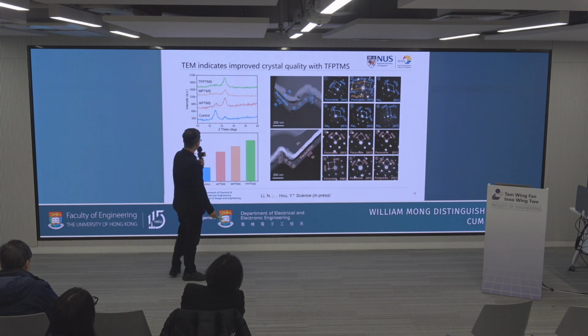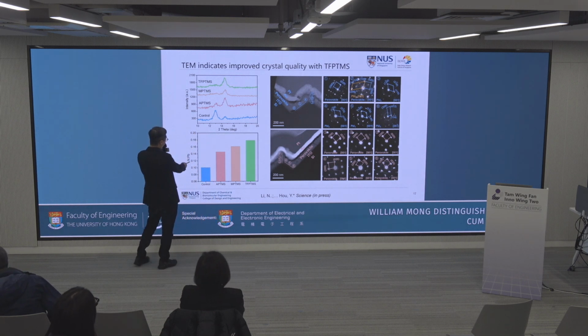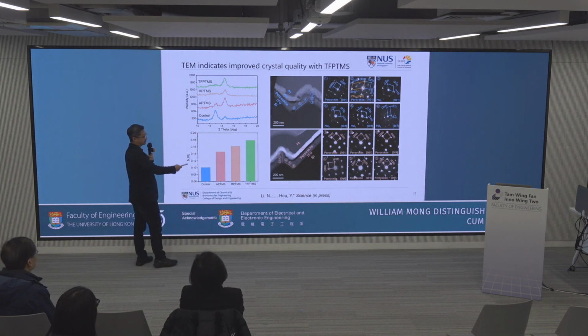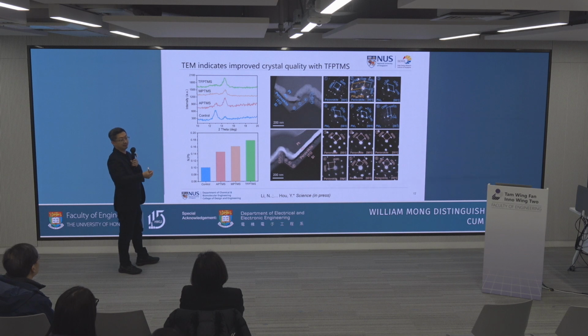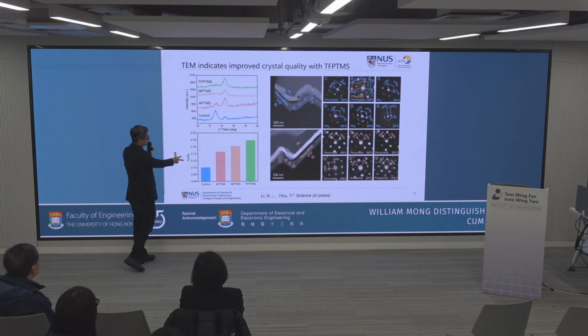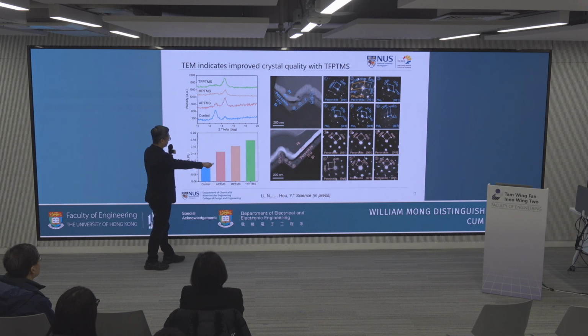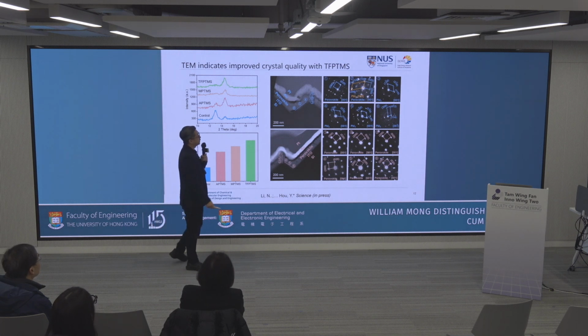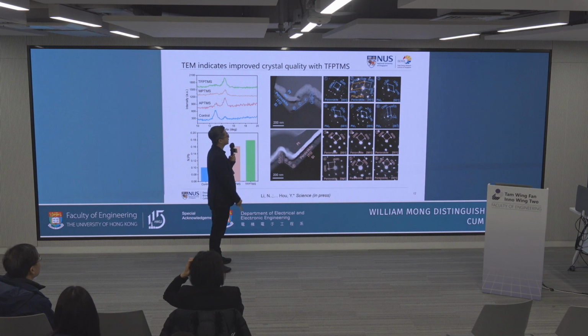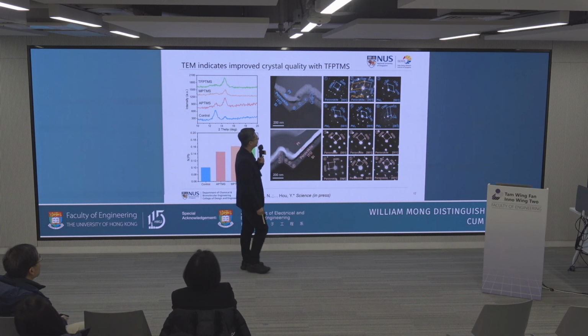And this EDX also can tell us the nitrogen and the lead ratio. Nitrogen represents the FAI, and so it can also give you the ratio of the organic and the inorganic, and you can see you have a better ratio here. And this is our TEM, and the result you can see here.